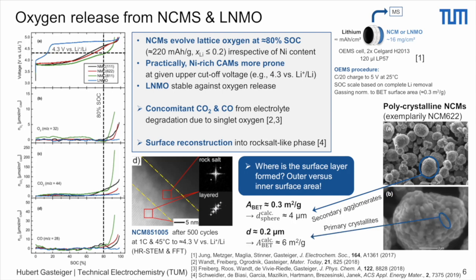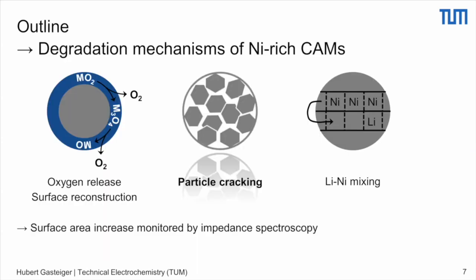On the other hand, if the material were to crack during cycling or during other treatments into the primary crystallites, which are about 0.2 microns in diameter, the spherical approximation would say that the BET surface area increases to about 6 meters squared per gram, right? And so the truth, of course, is somewhere in between. You start out definitely with a low BET, but what we find is that typically the BET area increases over the course of cycling. And this is what we will look at in the next section,